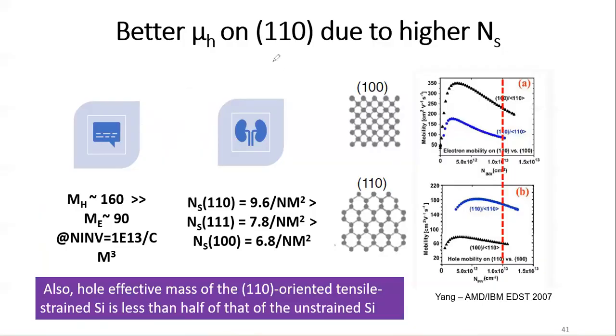People say, well, you could do 110. You can see from the right graph, 110 has a much higher hole mobility, and that's a good thing. That's the reason in FinFET we move our channel direction so that the channel plane sees 110. The carriers are moving along the 110 directions. And that's pretty good. But again, hypothetically at a high level, why does 110 have a higher hole mobility?